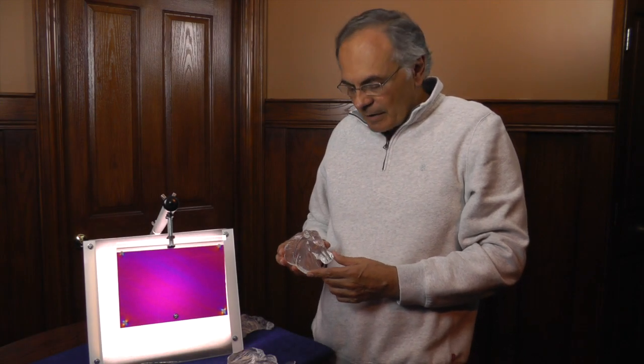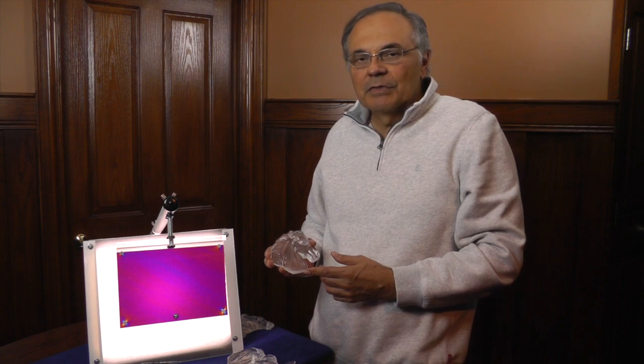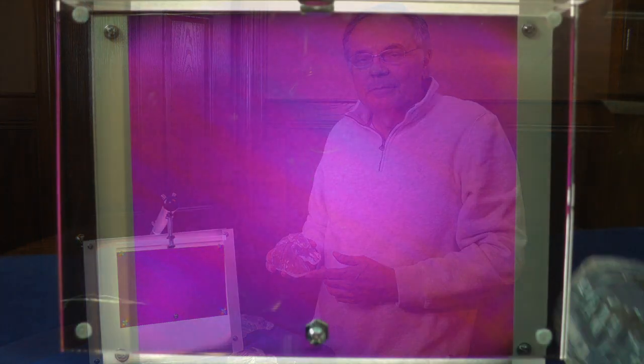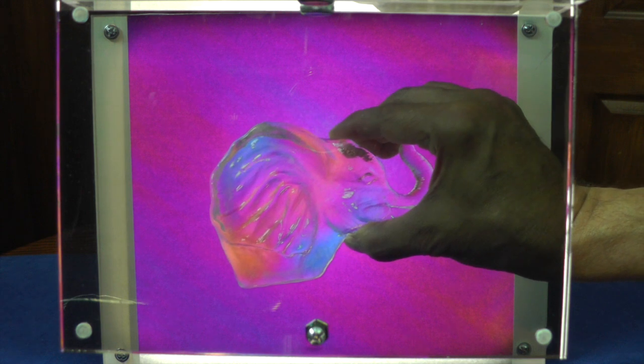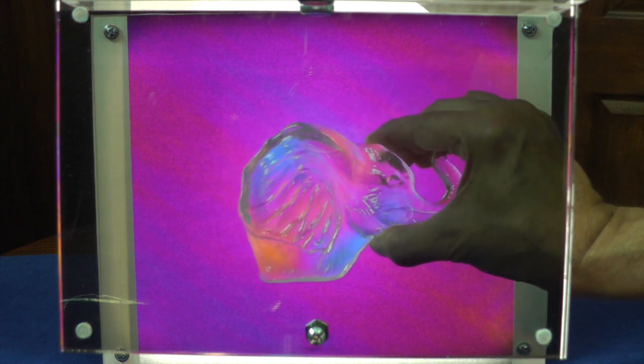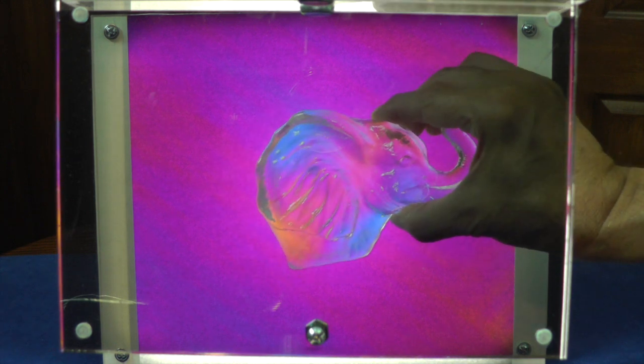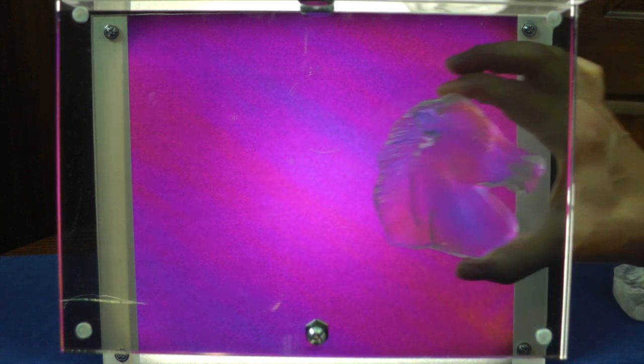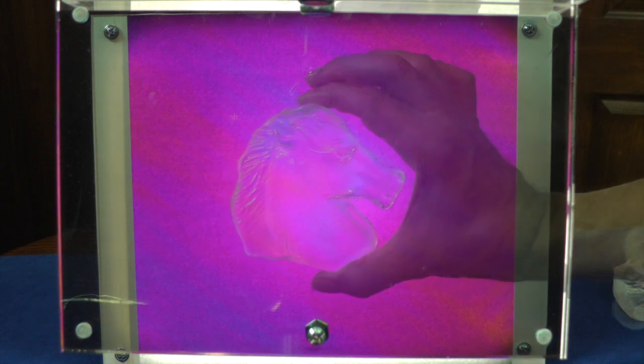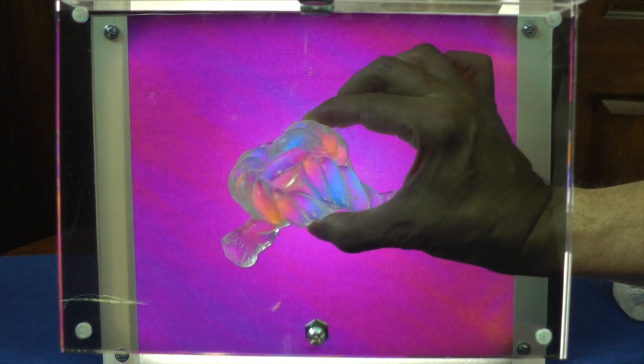We're going to take a look at some casted glass. These are some sculptures that I casted, and we'll see what they look like in the Polariscope. This is an example of very light strain. You can see how soft the transition is between the blue and the magenta and a little bit of the yellow. This is about 1.5 inches thick, and this is totally acceptable as a well-annealed sculpture.